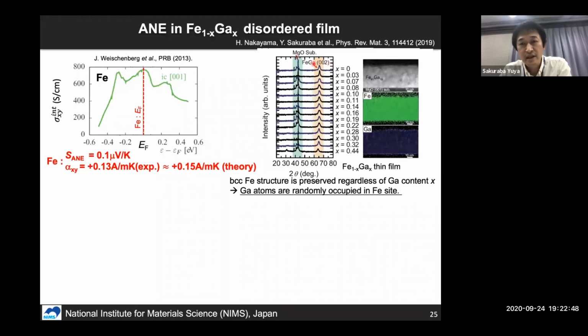So here you can see the XRD patterns for iron gallium thin films with different gallium concentrations. As you can see, we observed only the 002 BCC iron peak from x equals 0 to x equals 0.32. So this result suggests gallium atoms randomly occupy the iron sites and a randomly disordered BCC iron gallium forms in these thin films. As you can see in this EDS mapping analysis for one iron gallium thin film, we can observe an almost homogeneous distribution of gallium in our film.